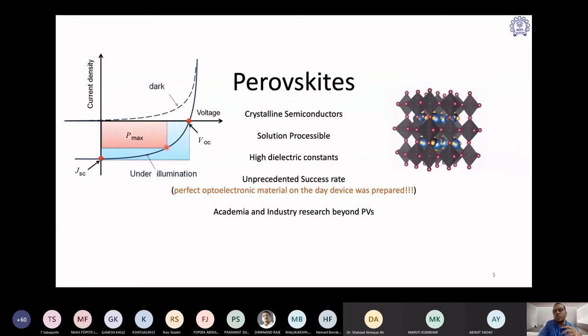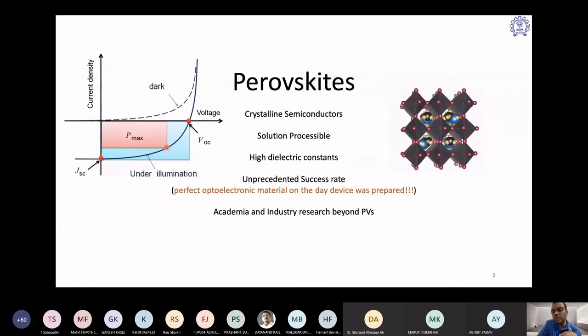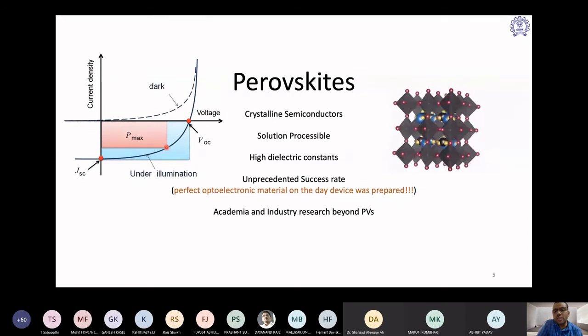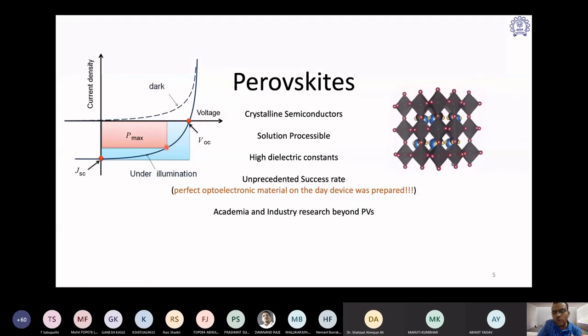First, you need to check whether you can form a crystalline structure or not by the tolerance factor. Second, you check whether thermal stability is there or not. If I heat up to close to 60 to 70 degrees Celsius for a few hours, whether my semiconducting material remains intact or not. If it doesn't remain intact, no need to work with that kind of semiconductor system for solar cell applications.